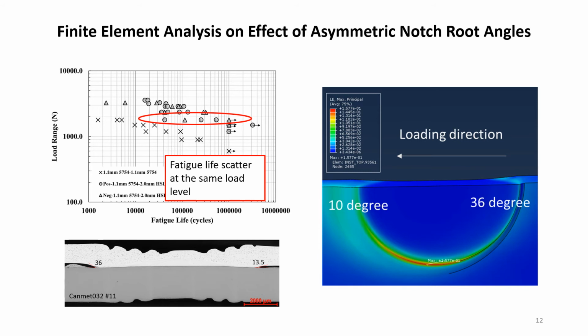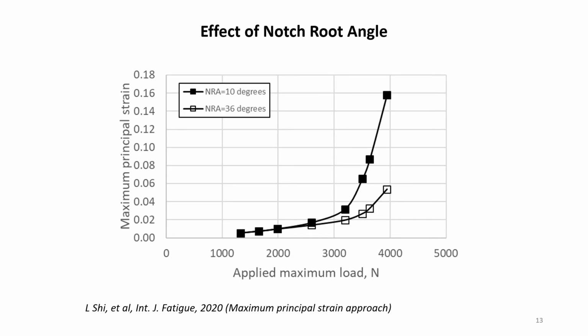We noted that there are notch angles in aluminum to steel stack-ups, so we used finite element analysis to calculate the maximum principal strain of the aluminum sheet with different notch angles. And the results show that less maximum principal strain occurs in the aluminum sheets with a larger notch angle. So the longer fatigue life in aluminum to HSLA steel is because less maximum principal strain occurs in the aluminum sheets compared to aluminum joined to itself.